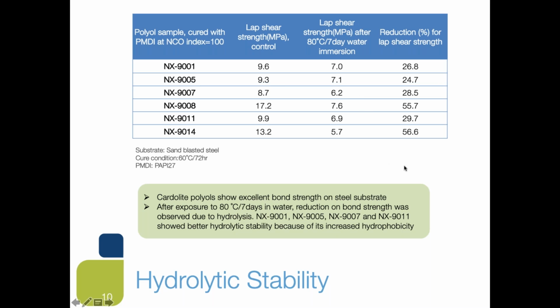From here, of course, you look at the product that has the least amount of lap shear reduction. What we learned is that the product that has shown the best hydrophobicity in general, even from the moisture sensitivity study, also shows the least reduction in lap shear strength. So 9001, 9005, 9007, and 9011 have shown the best hydrolytic stability in comparison to 9014 and 9008.